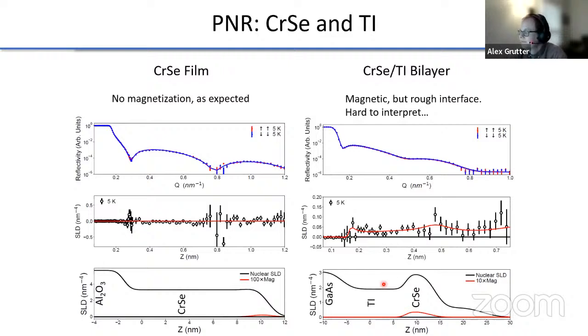So sometimes we end up in arguments about how we can really constrain our interface roughnesses in the modeling. Do we take a TEM measurement and constrain the roughness that way? Well, sometimes you can do that with topological insulators, usually not. Also with X-rays, if you do an X-ray reflectivity measurement, the coherence length of the X-ray is different from the neutron. And so you may get the same thickness answer for X-rays and neutrons, but different roughness answers. And so usually we treat the X-ray roughness as the lower limit for the neutron roughness because the wave packet is